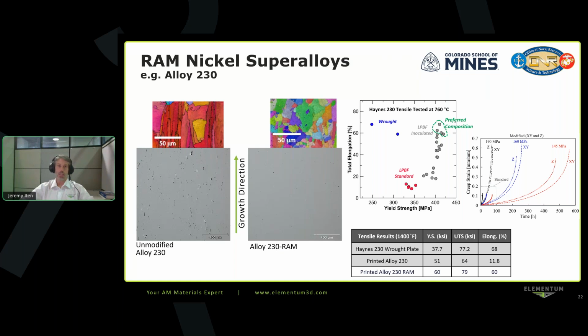You can see the elongation is comparable to the traditionally produced wrought plate, but the strength is actually significantly higher. You can also see, even if you look at creep, the creep performance is also much improved compared to the unmodified alloy in the printed form. Those are showing the creep performances at different stresses, and you're getting much longer creep life as well as less creep strain for a given amount of time and stress.